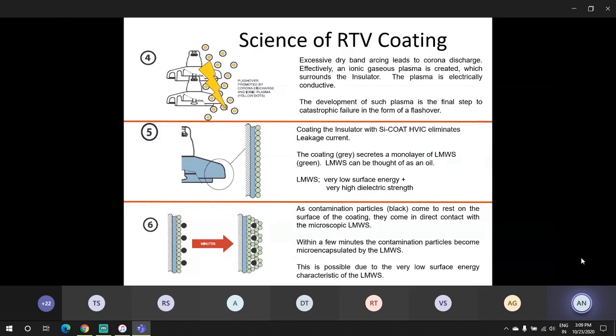So what we propose is to apply a very thin coating, approximately 400 to 500 microns, on the insulator. This rich concentration of silicone polymers secretes a monolayer of silicone molecules, which we call in technical terms the low molecular weight silicones. And it has two distinct properties. It has a very low surface energy and a very high dielectric strength.